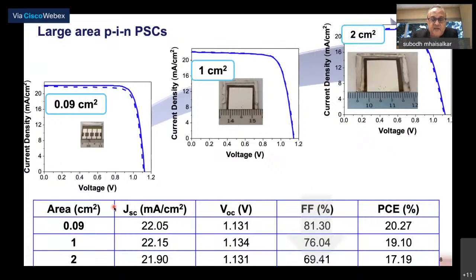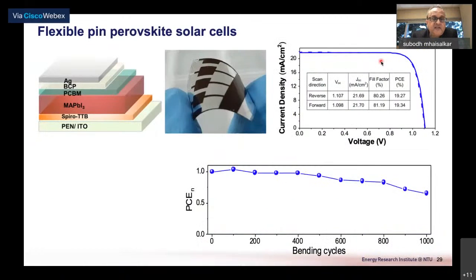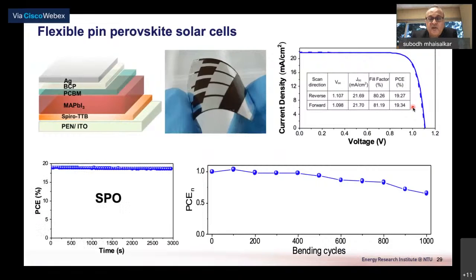So from a scaling perspective, we do drop a little bit from 20.27% to about 17+% as you go to 2 centimeters square. And this is something that needs a lot more study. We have also tried a deposition of these same stacks on flexible substrates. And we are very encouraged that even with deposition on flexible substrates, the overall efficiency is maintained. The stabilized power output is also unchanged with time with these flexible devices. So this also raises the possibility of perovskite tandems that could be deposited on flexible substrates, and that is a topic that we would touch upon in the years to come.